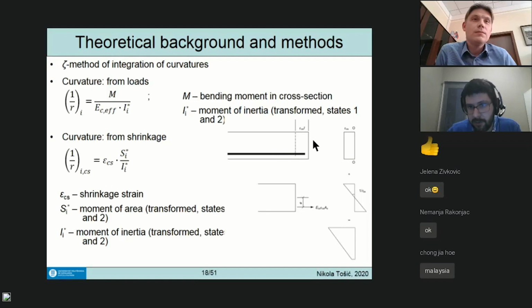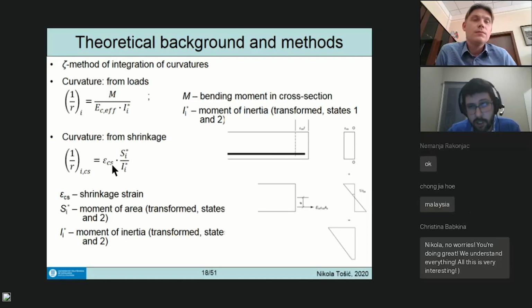Simply, it is the area of steel times the eccentricity. You will see in different places different formulations, usually written with epsilon times alpha, which is the modulus ratio, and then S over I. But in that case, S is just literally the area of reinforcement times the eccentricity. Here, because I put this star, it means it's already transformed, so the ratio of the moduli is already within S. You will see it later in the calculation.